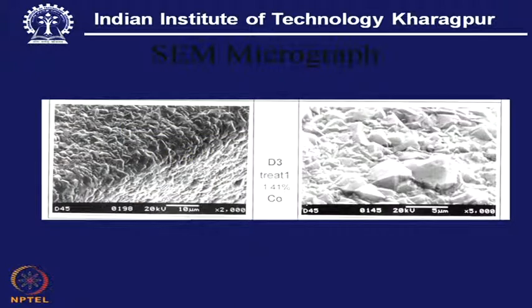Now, here we can give another example. This is the diamond coating, and again it is the SEM picture. Now, it is the cutting tool, and if we know that this is going to be the cutting edge, this is the top face of the tool and that is the flank of the tool, the surface is relatively rough compared to any PVD coating, this is also a fact. However, it is well covered, that means from this we can also have a good inference that the process technology allows us to have a full coverage of the cutting edge, and it is a well built cutting edge, it is integral, this coating is integral with the substrate.